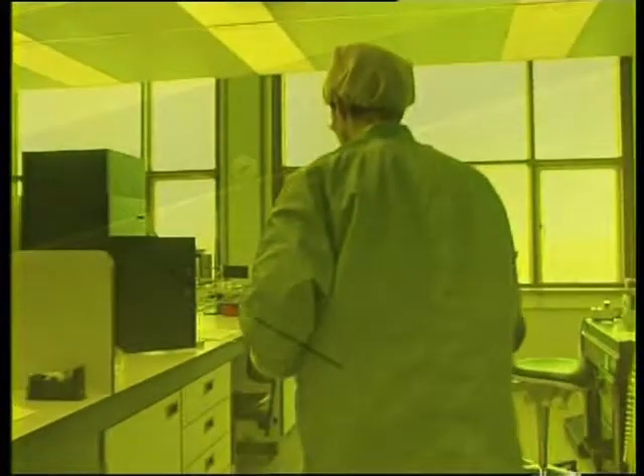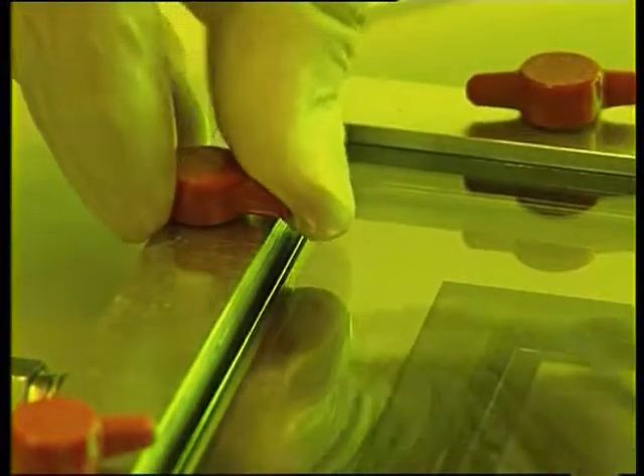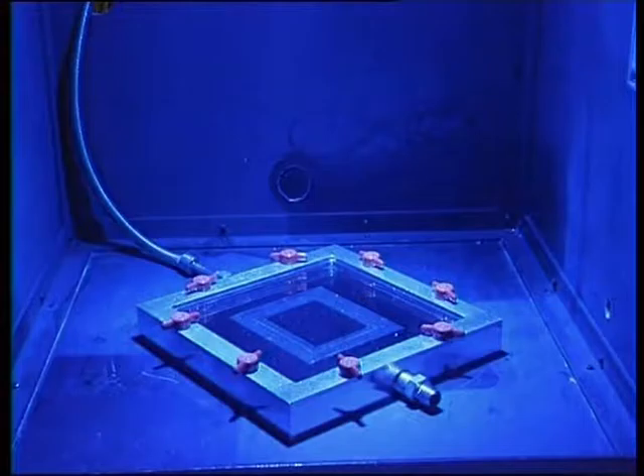In the Philips Paint Well LCD process, displays are fabricated by simple coating techniques. First, a liquid is dispensed on the edge of the substrate. This liquid contains all the necessary ingredients to make a liquid crystal switch. The so-called doctor blade is used to coat the substrate with a thin wet film.